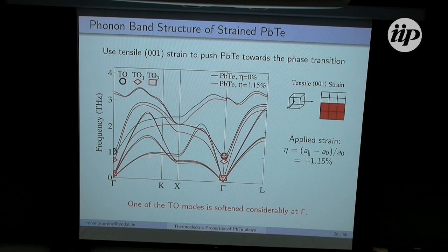Now you can see there are maybe a few differences away from the zone center, but the major difference occurs at the gamma point. You can see in the case of lead telluride, this TO mode has dropped from 1 terahertz down to about 0.1 terahertz in the strained lead telluride case. Now I will just briefly mention that 1.15% of strain is rather a lot of strain to apply in this case, but the goal here is maybe to look at this more as a thought experiment in a way, and to see what happens if we push it to the verge of the phase transition.